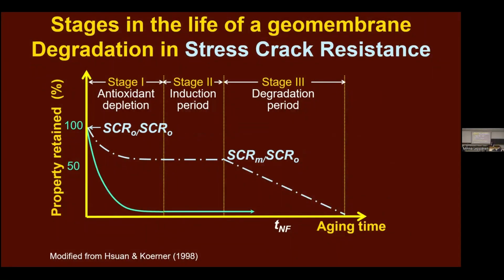Now, once they've depleted, there's an induction period, and then the polymer starts to break down. And that's when we drop from SCRM down to failed. I do want to point out to you that the drop from SCR naught to SCRM is not degradation. There's nothing wrong with the geomembrane. All that's happening is those residual stresses from manufacturing have relaxed.